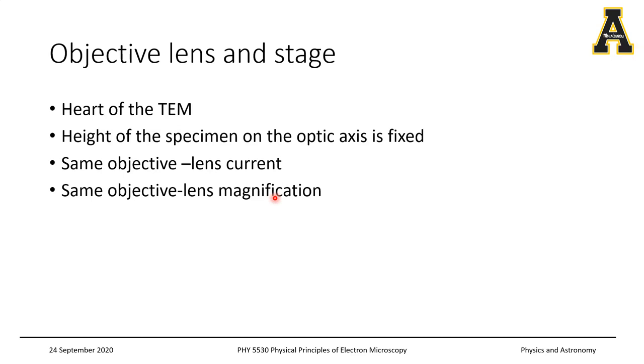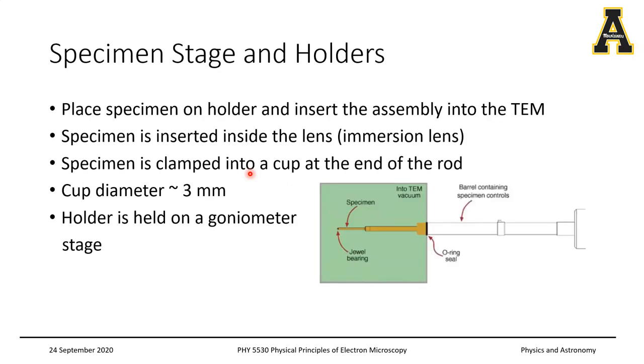In most scanning electron microscopes the lenses are pinhole lenses, so the sample is outside the electromagnetic lens. As a user you have control in determining the distance between the lens and your specimen — the working distance — and that gives you control of the field of view and magnification. But that is not available in TEM, precisely because you want to minimize any kind of aberration that are present in the pinhole lens but not in the immersion lens. Typically the specimen is inside an immersion lens.